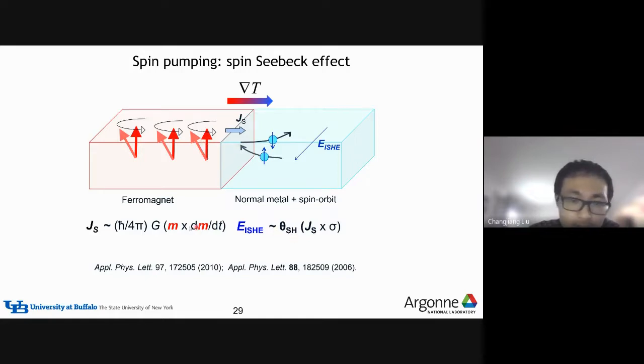As a result, there will be a spin current flowing across this interface due to this precession of magnetization. So it turns out that once you use a heavy metal, this spin current can be measured using an inverse spin Hall effect. Because of the large spin orbit coupling, this spin current can be deflected towards one direction. Basically, you get a charge current, which produces a large voltage.